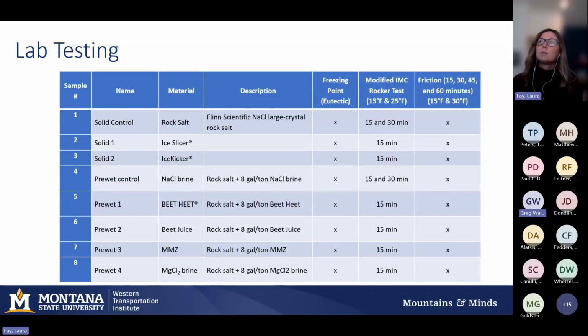We measured freezing point and the solubility limit to determine the eutectic temperature. We used a modified ice melting rocker test. Because we're using solid products, they had to modify the test method for that. That was done at 2 temperatures. And we did a friction analysis where we looked at, as these are applied to the pavement, what happens to the friction on the pavement surface. And again, that was done at 2 temperatures as well.